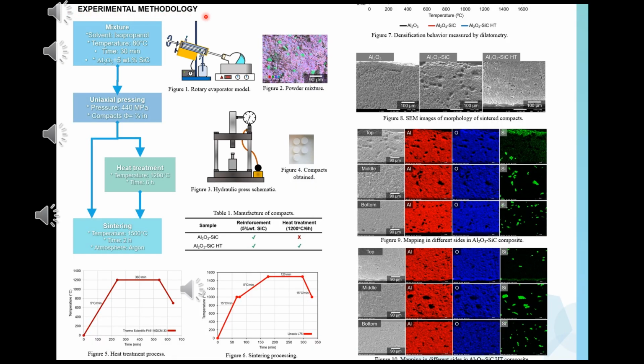Experimental methodology. A mixture of aluminum oxide with 5% wt of silicon carbide reinforcement was produced by roto-evaporation, using isopropyl alcohol as a solvent. Then, from the mixture of powders, compacts were manufactured at 440 megapascals by uniaxial pressing. Some samples had a heat treatment at 1200 degrees Celsius for 6 hours in air before sintering. The sintering was carried out in a vertical dilatometer, Linseis L75V, up to the temperature of 1500 degrees Celsius for a time of 2 hours under protective argon atmosphere. The sintering curve can be seen in Figure 6.